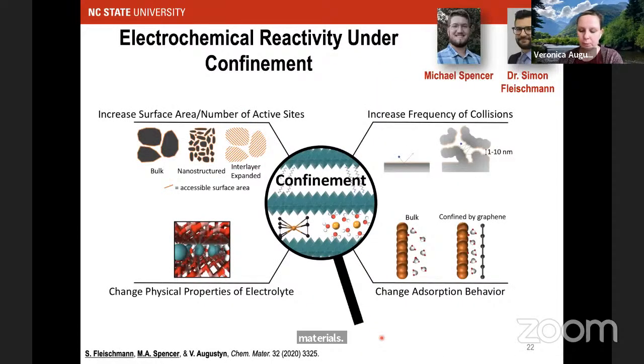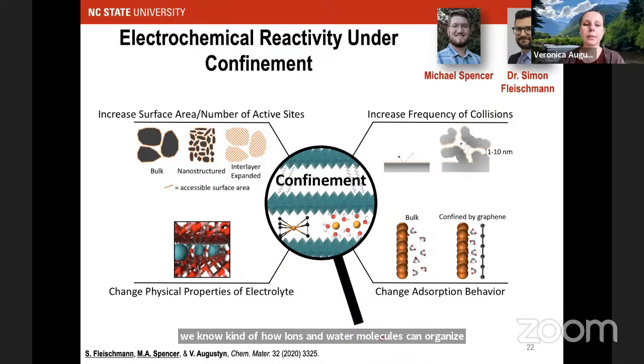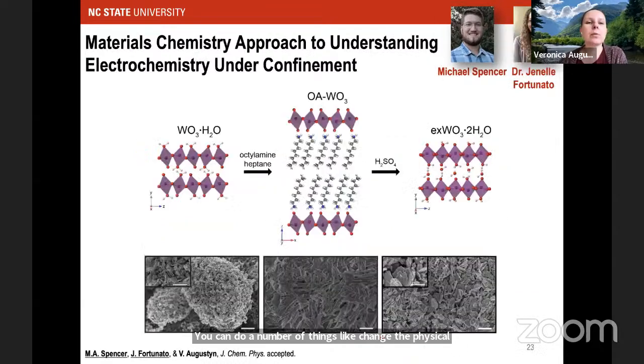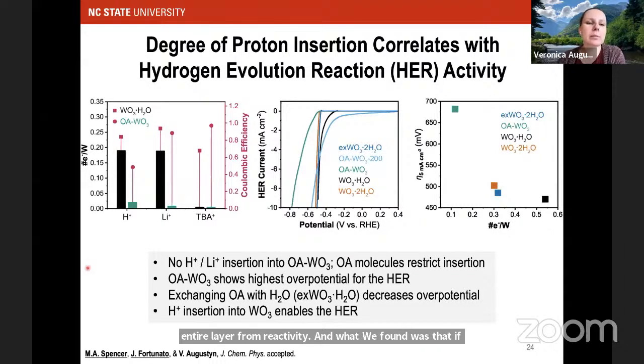I also wanted to touch upon really quickly the concept of electrochemical reactivity under confinement, which is kind of the next step, now that we know how ions and water molecules can organize themselves into confined spaces: can we look at subsequent electrochemical reactivity? And there's a lot of beautiful theoretical work done to suggest that this should be the case. You can do a number of things like change the physical properties of electrolytes or change adsorption behavior under confinement. We wanted to answer this question from a materials chemistry approach. And so to do that, we synthesized these hybrid tungsten oxide octylamine materials that essentially block the interlayer from reactivity. And what we found was that if you block that interlayer from being able to insert protons, you see a much higher overpotential for the hydrogen evolution reaction. So showcasing how important these cation insertion or proton insertion processes can be for interfacial reactivity.